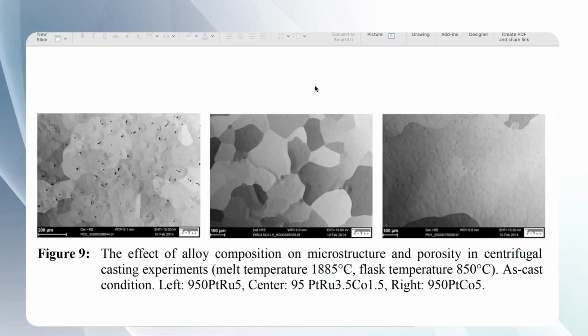Yes, and they're on the inside. Oftentimes they're not on the outside of the metal, they're on the inside, they're everywhere in the cast part. This microporosity, of course, must be avoided, or it can be repaired by hot isostatic pressing. But of course, it would be better to avoid it from the beginning. And here we see that the small addition of cobalt also helped - it completely avoided this microporosity. I think that's also a very interesting result of that work.